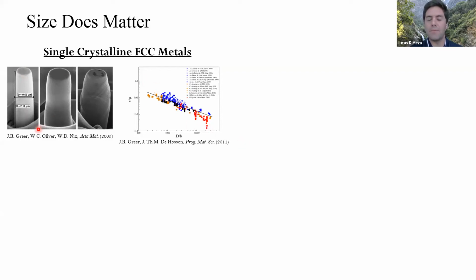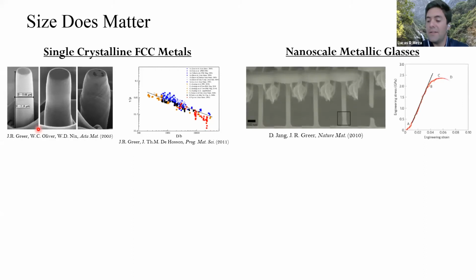If you're able to make something that's 10, 20 nanometers in diameter, you get near the theoretical strength of the material. For intrinsically brittle materials at the macro scale, you can actually have them become ductile at the nanoscale. I don't know how many of you are familiar with metallic glasses, but it's an amorphous metal material that is generally fairly strong but brittle at the macro scale. You can actually get to length scales where you can suppress that brittle shear band localization, and you can get some ductility into your intrinsically brittle material.